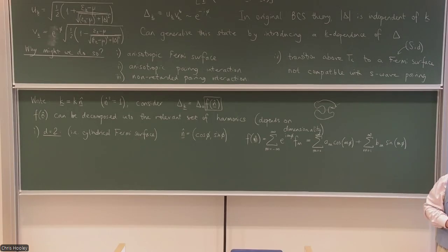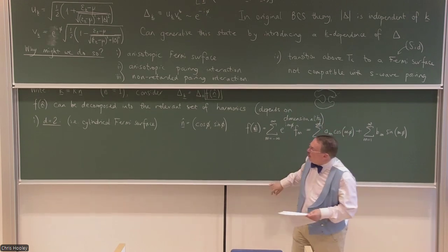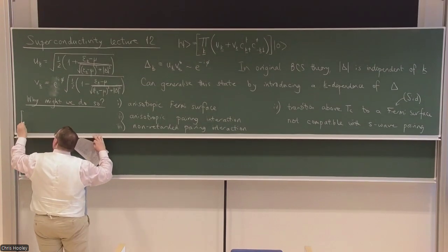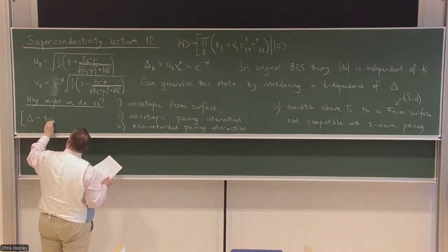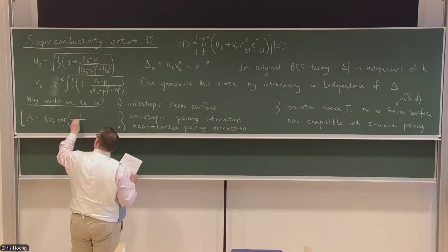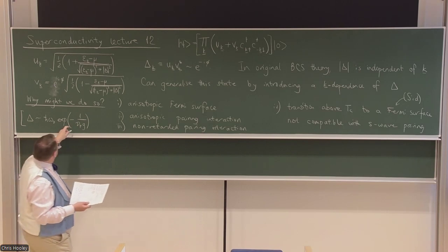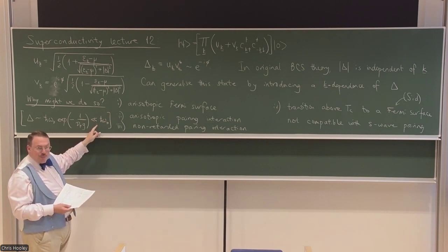Because of the fact that the pairing is not in the window of a Debye frequency. It's actually because the superconducting order parameter that we got from the BCS gap equation is small. So it is true that the pairing is only in a window of the Debye frequency, and so we don't care about stuff beyond that. Let me just give this as an aside. But actually, what we calculated from the gap equation was that delta goes like the Debye energy times this exponentially small factor. So actually, this is much less even than the pairing interaction window.